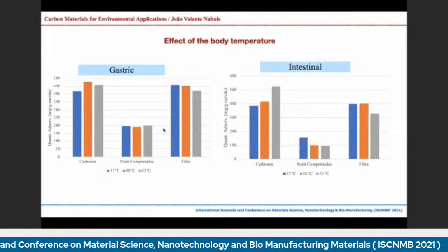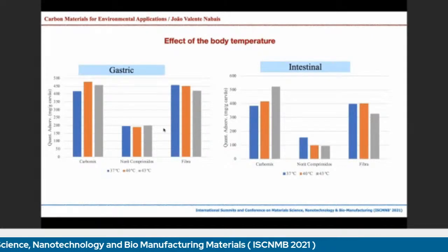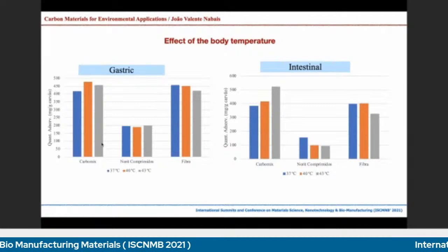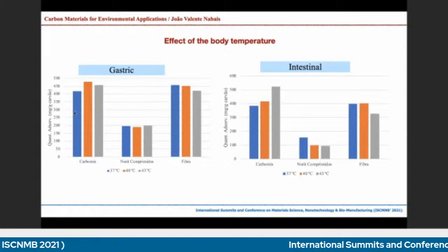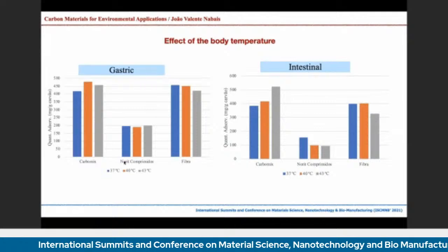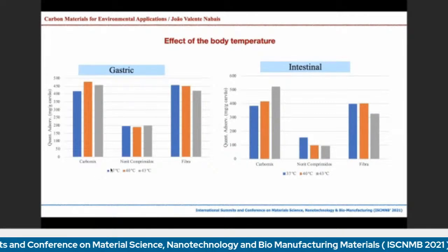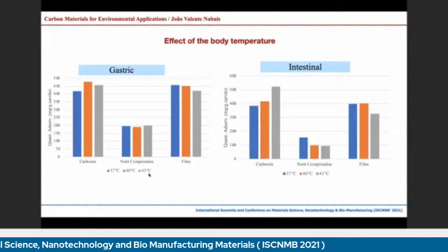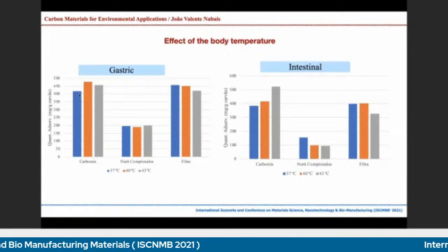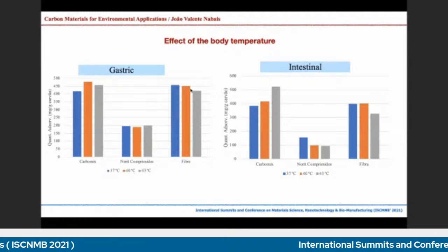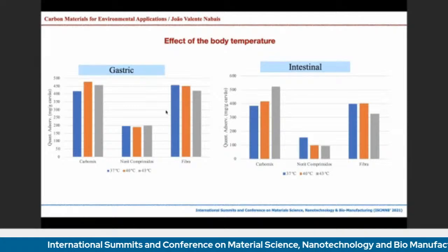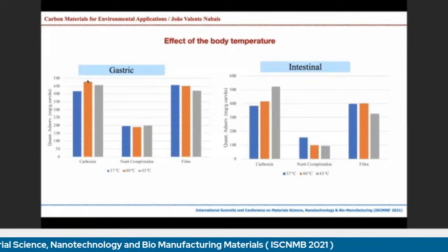We did one study which was quite interesting, because we studied the influence of the temperature, and we concluded that this is the amount absorbed, milligrams per gram of carbon. Sorry, this is in Portuguese. If you pass from 37 Celsius degrees to 43, you can see that the temperature does not influence that much the absorption capacity of the materials, which is quite interesting, because if someone has a fever, that fever does not impact the absorption of the drugs by the activated carbons. But